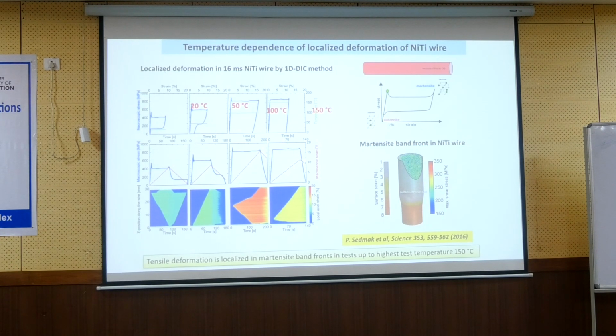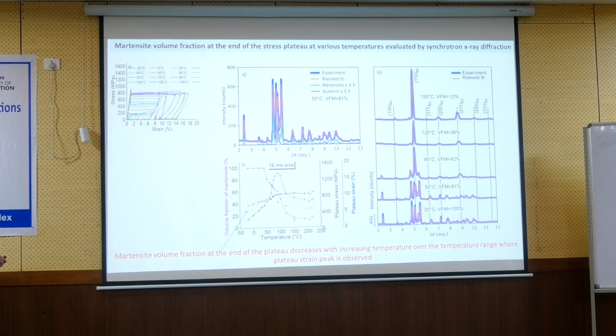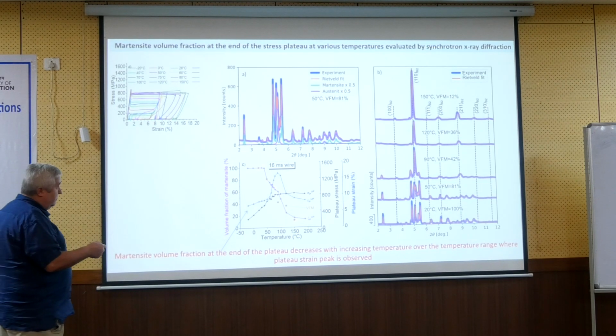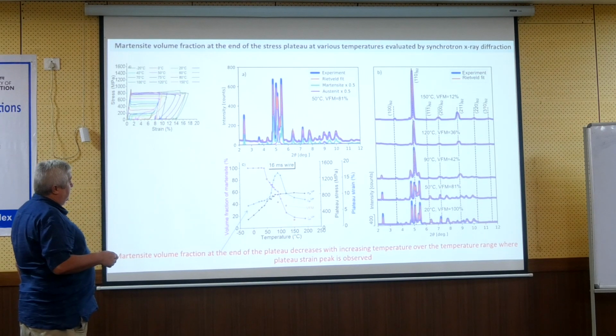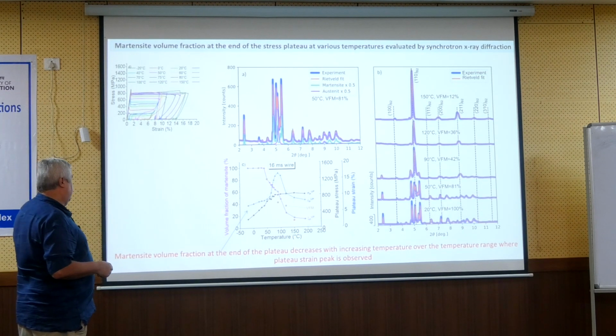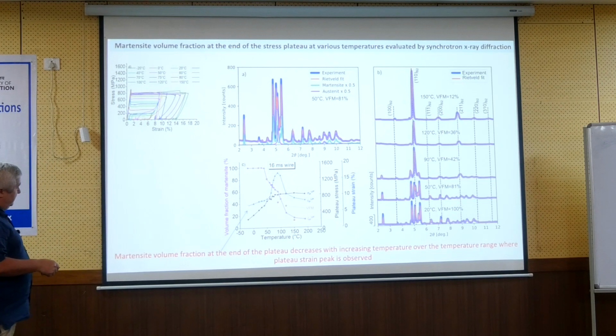Why is there this maximum? This was explained by using in situ X-rays. Here is the strain maximum, and at the end over here we look into the material by X-rays, and you will find that at room temperature, which is here, this is the evidence for martensite. The band, the martensite, when it propagated here, the microstructure in the martensite is fully martensitic.